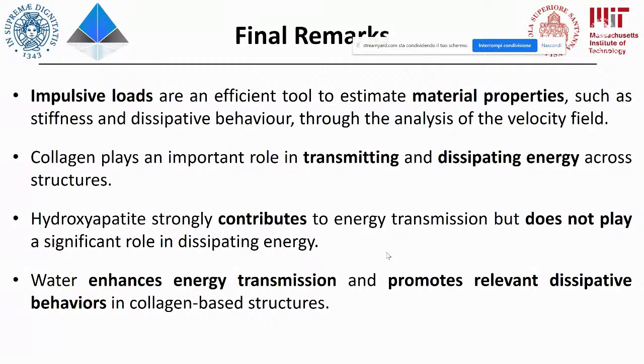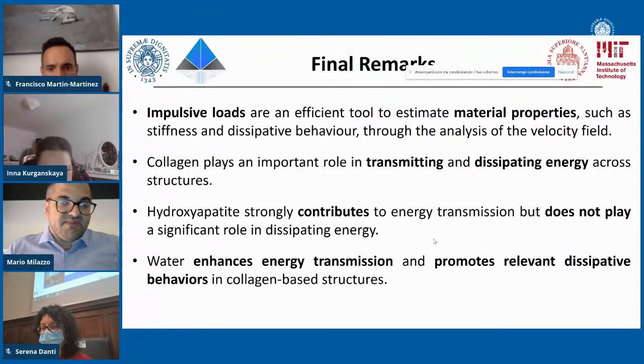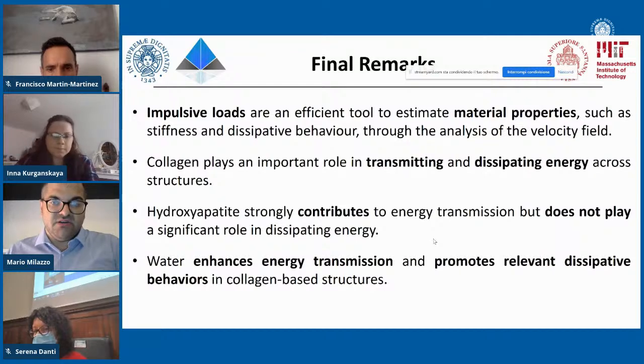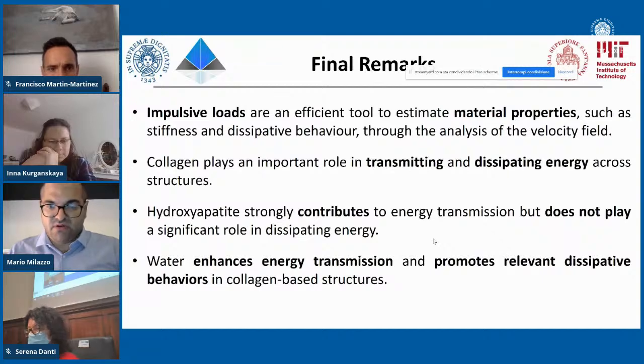Collagen is the main actor in dissipating energy, especially because when we are speaking about mineralized fibrils, hydroxyapatite, of course, is a very stiff material, so collagen is the one that is playing the main role, together with water that is promoting the dissipative behavior, is enhancing the behavior that is persistently promoted by collagen, while hydroxyapatite contributes to energy transmission since it is a stiff material, so it's giving, let's say, a boost to energy transmission, but doesn't play a significant role in dissipating energy.